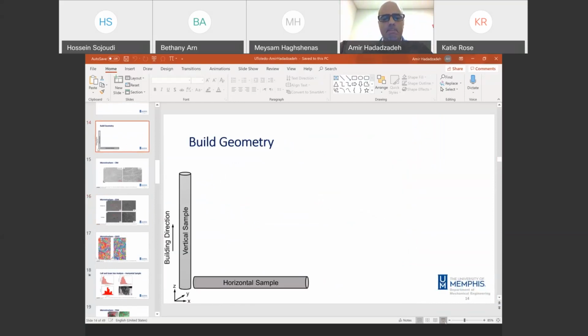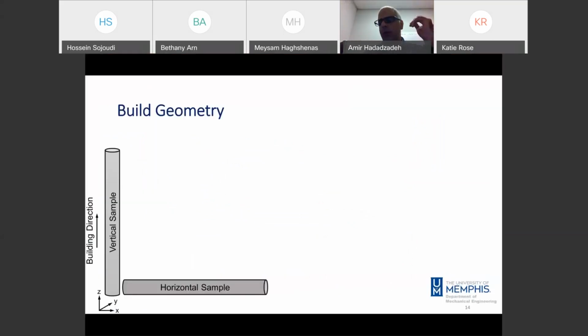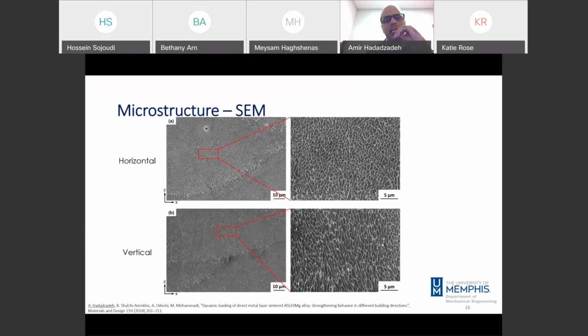So let me start with this slide here. As I mentioned, if we want to fabricate a component with a very simple shape, like this cylindrical shape, we can fabricate it in different directions because we have this freedom in the SLM process. And that's a big question in this context. If we change the geometry, we are changing the thermal history experienced by the material during cooling, because we have a solidification process in SLM, and that solidification is controlled by the thermal gradient and thermal boundary conditions. If we change the geometry, we are changing those boundary conditions, and as a result,